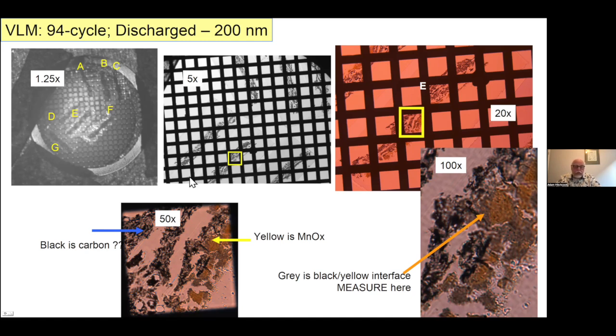And then we're going in finer detail. After looking at all of these, I felt that this one actually had the morphology I was expecting from the way we prepped the sample. So this is then an expansion of it, and then an expansion some more. It's only when we went up to 50x magnification that we started to see the nature of the sample. It turns out these yellowish regions here, and we confirmed this by the STXM, are actually the manganese oxide cathode material, and the black materials here are the carbon support that it's using for electrical contact to the outside world. What we're interested in is exactly that interface between the carbon and the manganese dioxide, or one of the interests. And these gray areas here are most likely a mixture of the two, which we would only find out when we do the STXM experiment.